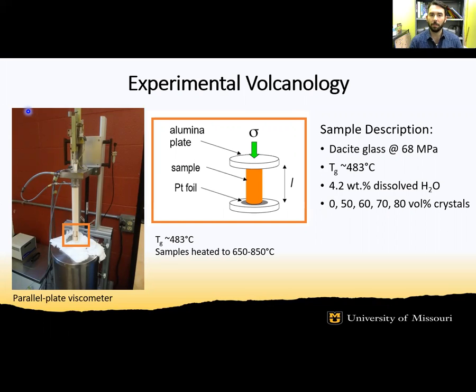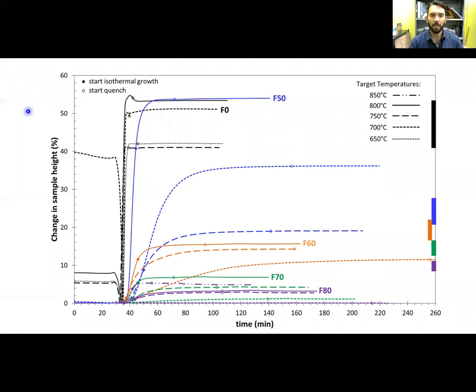Once each sample was heated beyond its glass transition temperature, the melt was able to relax from its high-pressure configuration to atmospheric conditions, allowing degassing to occur. Instead of measuring uniaxial deformation or compression, we utilized our parallel plate viscometer to measure vertical expansion of the samples. This is the raw data from the parallel plate showing sample inflation with time. Each color and F number corresponds to crystal fraction in volume percent.